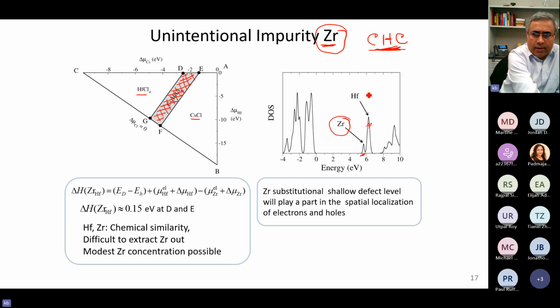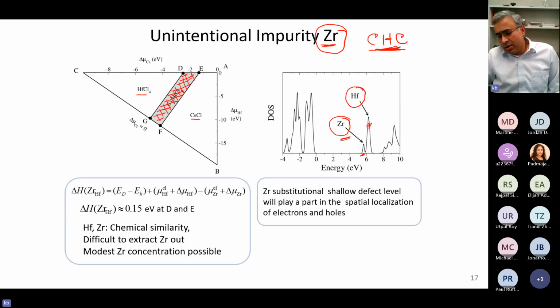In this self-activated material, we have hafnium related emission centers. And since zirconium can be an unintentional impurity, zirconium can also become part of that. But it will have a separate emission wavelength because it's zirconium, not hafnium. So there will be at least two different types of emissions because of this impurity.